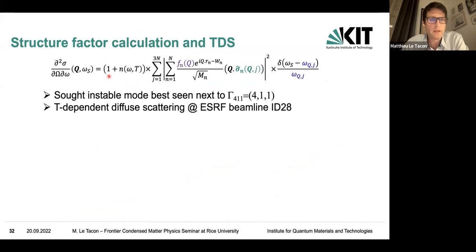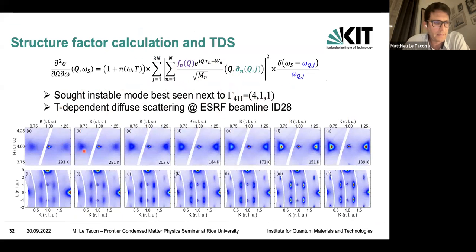Okay, so we ran some structure factor calculations, and that tells us that the best place to look at the soft mode would be next to the 411 zone center. And that's where we decided to go and take some temperature-dependent diffuse scattering. And that's how it looks.